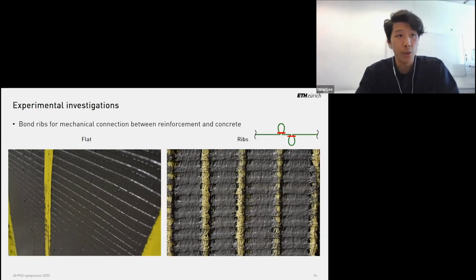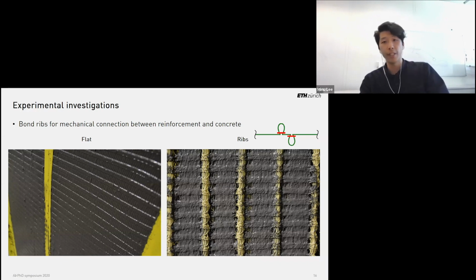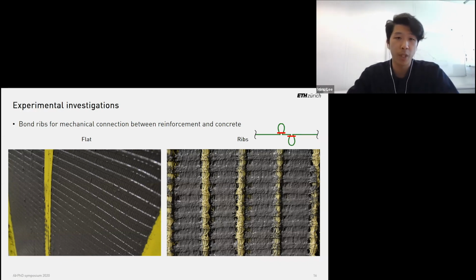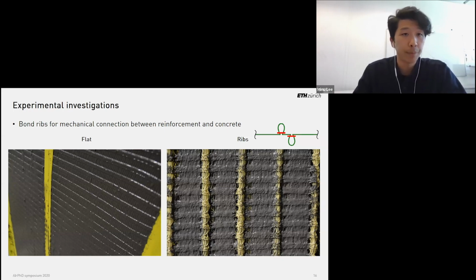Lastly, we also introduced some spatial features in form of ribs in some specimens. Since the surface is quite flat after coating and the concrete is not able to flow through it due to the closed surface, as we can see on the left image, we want to improve the mechanical connection between reinforcement and concrete by creating these bond ribs. They are formed by folding the textile and closing the resulting loop, as is schematically shown in the top right corner. This feature could also be automatically manufactured in the knitting machine.